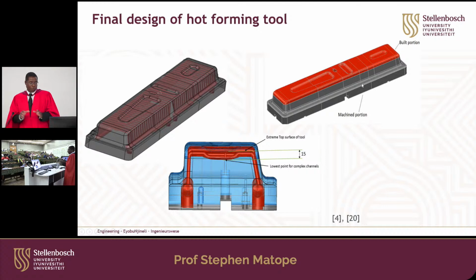For the bottom part, we did the machining itself, the drilling of the holes, especially these ones here. But the part where we wanted the cooling to be more, which was near the surface, that's where we did the additive manufacturing, the 3D printing, layer by layer. Coming with those geometries, as you can see, it's no longer straight as in the first case. Now they follow the profile of our final product. That meant the water channels were closer to our product, so that heat can quickly be removed.